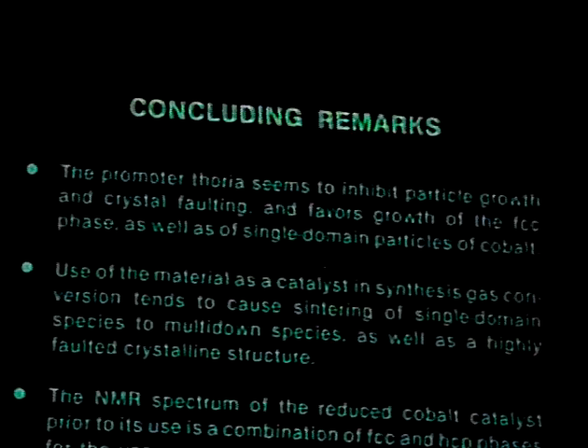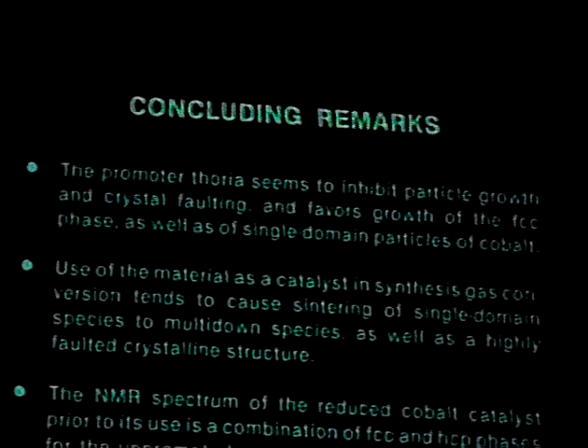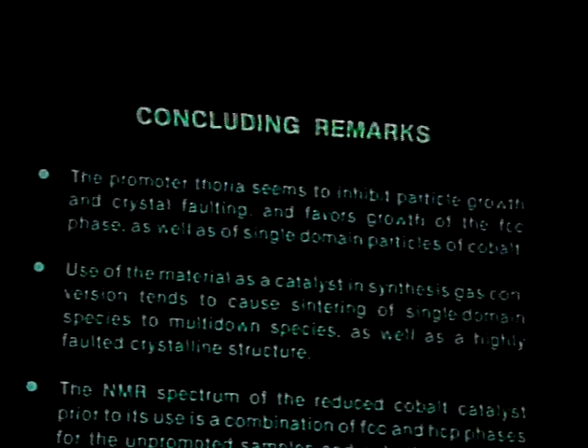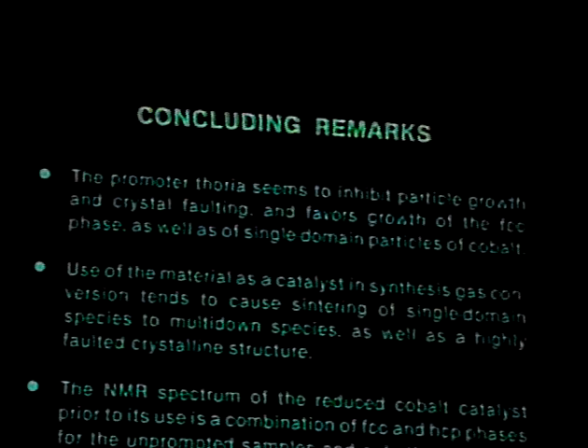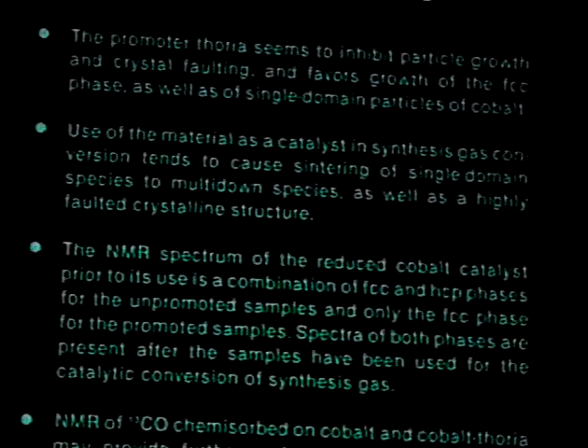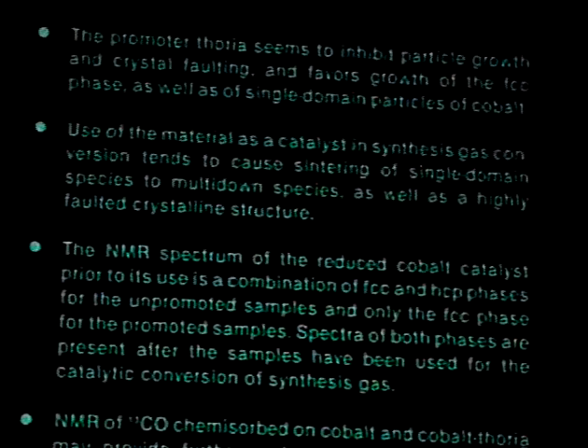So in conclusion, we say that the promoter thoria seems to inhibit particle growth and crystal faulting and favors the growth of the FCC phase as well as the growth of single domain particles of cobalt. Then use of the material as a catalyst in syngas conversion tends to cause sintering of single domain species to - that's a mistake there, it should be multi-domain species - as well as a highly faulted crystal structure.